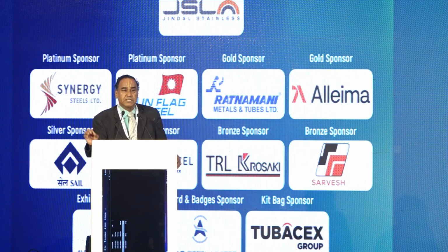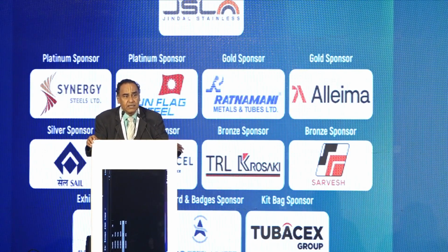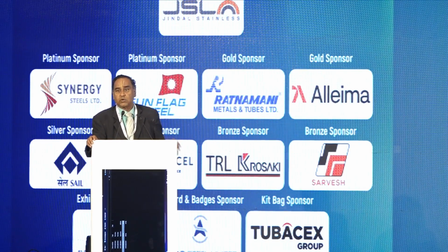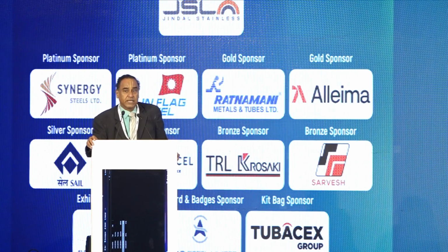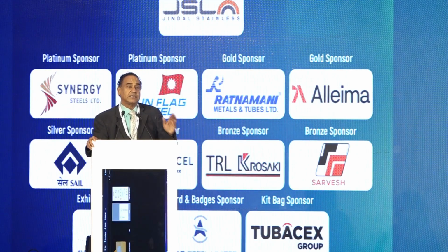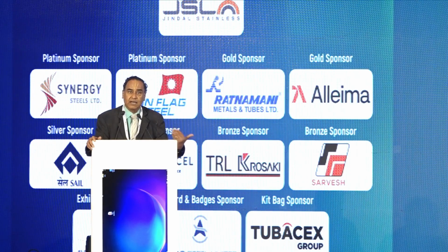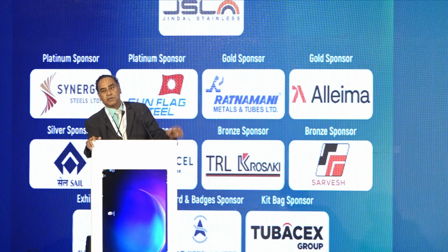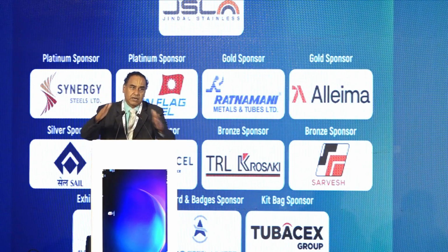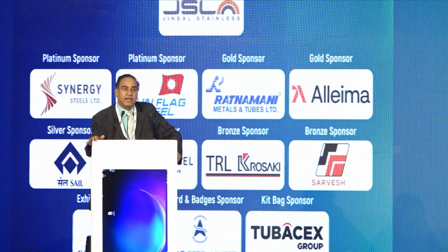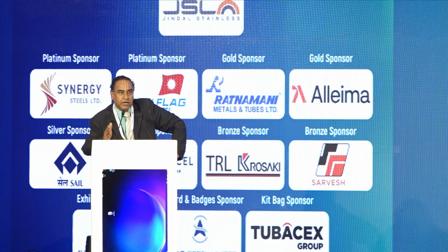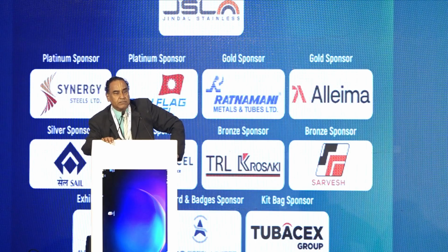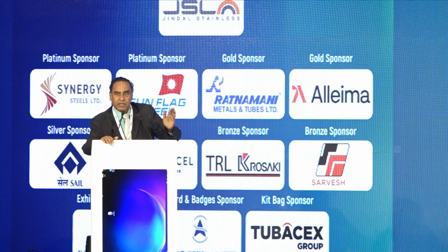When the chloride is present and beyond 60 degrees centigrade, it becomes prone to stress corrosion, chloride stress corrosion cracking, and because of that, they are not used in their solid form. Either they can be used as a clad form, where the base material, the backing material, will be a cheaper material like carbon steel or chromoly steels, which can withstand the higher temperature and higher pressures, etc. And the face of the plate,